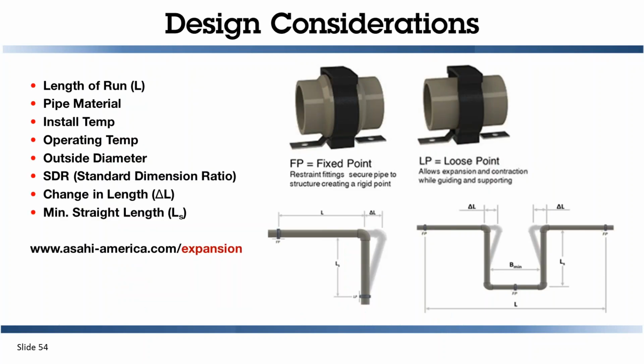The preferred method for plastic installation is allowing it to move as it would be naturally. So there are two methods here. On the bottom right, we see two images. We see an elbow that will allow the material to move, and we see a U-bend, which will lock the piping in place down at this bottom fixed point, and the two corners will bend into each other. The height of this riser, or the minimum distance L, needs to be designed so we're not putting extra stress on the elbow with the expansion and contraction of the pipe.